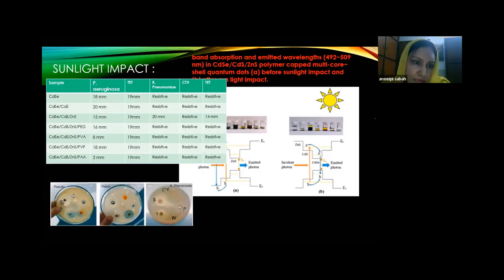For cadmium selenide, the inhibition zone length was measured at approximately 18 millimeters, and for pneumonia it is completely resistive. Similarly for cadmium selenide, cadmium sulfide, zinc sulfide dots, and with the different polymers, we also find them showing an inhibition zone.